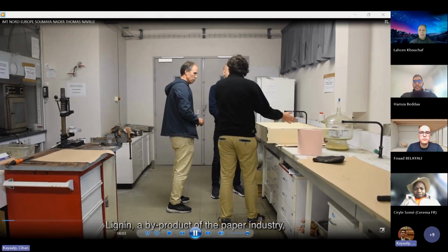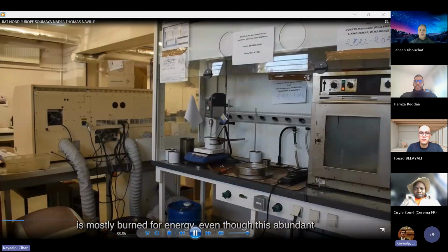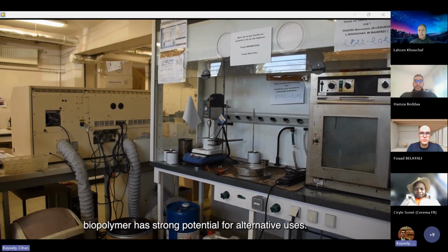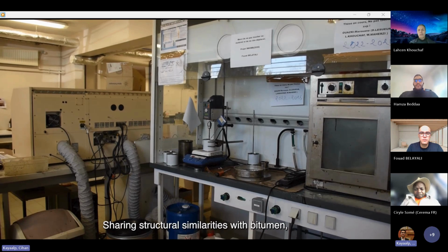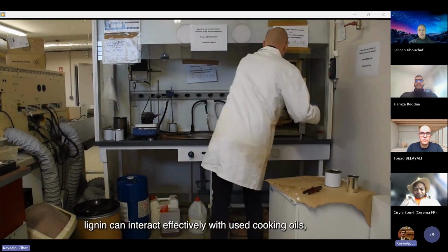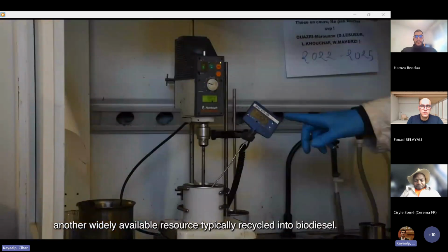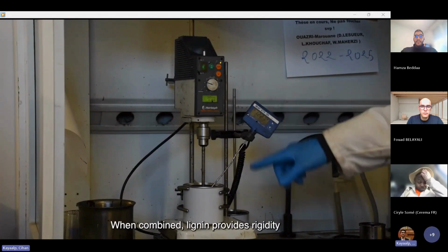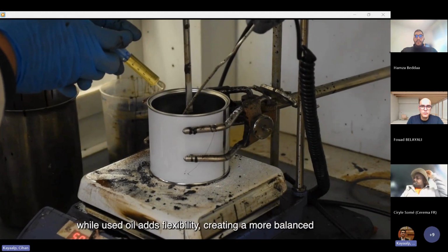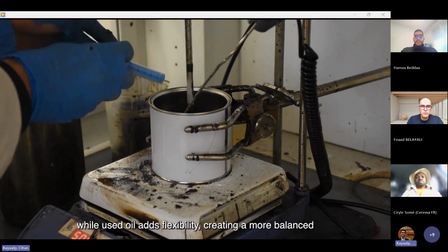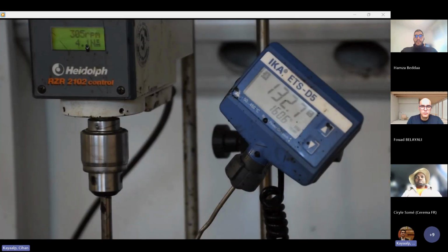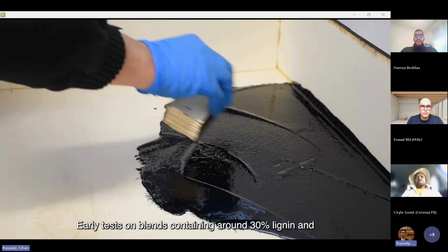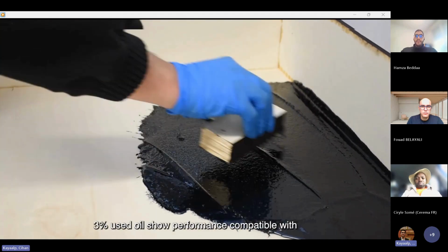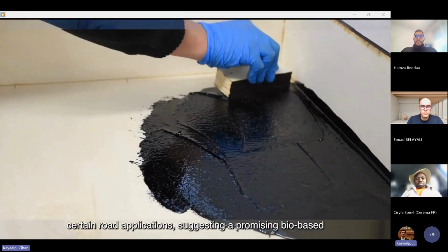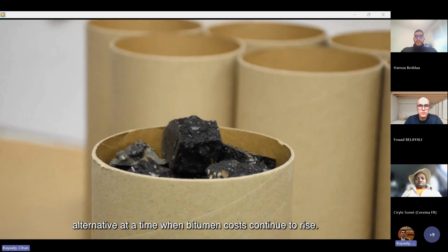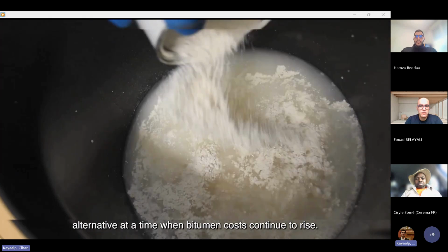Lignin, a byproduct of the paper industry, is mostly burned for energy, even though this abundant biopolymer has strong potential for alternative uses. Sharing structural similarities with bitumen, lignin can interact effectively with used cooking oils, another widely available resource typically recycled into biodiesel. When combined, lignin provides rigidity, while used oil adds flexibility, creating a more balanced material suitable for bituminous mixtures. Early tests on blends containing around 30% lignin and 3% used oil show performance compatible with certain road applications, suggesting a promising bio-based alternative at a time when bitumen costs continue to rise.